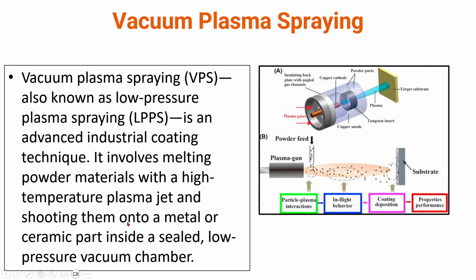It involves melting powder material with a high temperature plasma jet and shooting it onto a metal or ceramic part inside a sealed low pressure vacuum chamber. This job is done inside a low pressure vacuum chamber. That's why it is called vacuum plasma spray, also known as low pressure plasma spray, an advanced industrial coating technique. But as the pressure is low, coating adherence to the surface will not be as much as the plasma spray.